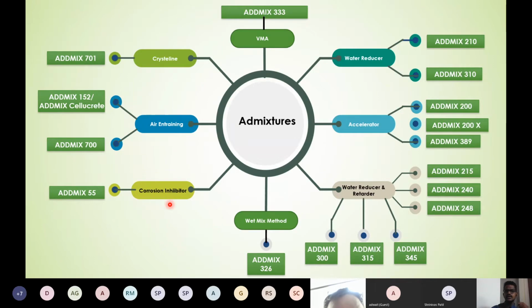So next is corrosion inhibitor admixtures. For corrosion inhibitor admixtures, we have Admix 55. The next is air entraining admixtures. Under air entraining admixtures, we have two admixtures: Admix 152, which is now known as Admix Cellucrete, and the second is Admix 700. The next is crystalline admixtures. For crystalline we have Admix 701, which is recently developed. We are going to talk about this Admix 701 later on. The next is VMA, that is viscosity modifying admixtures, which is Admix 333. This VMA is mostly used in self-compacting concrete.